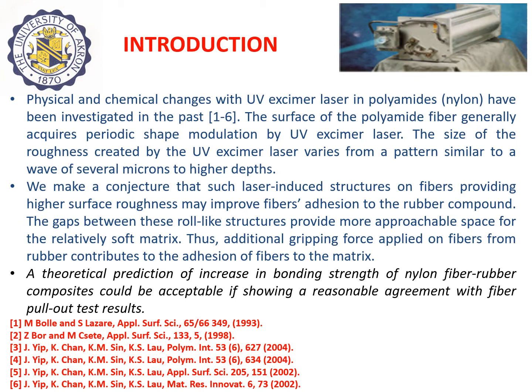We make a conjecture that such laser-induced structures on fibers providing higher surface roughness may improve fibers' adhesion to rubber compound. The gaps between these roll-like structures provide more approachable space for the relatively soft matrix. Thus, additional gripping force applied on fibers from rubber contributes to the adhesion of fibers to the matrix. A theoretical prediction of increase in bonding strength of nylon fiber rubber composites could be acceptable if showing a reasonable agreement with fiber pull-out test results.